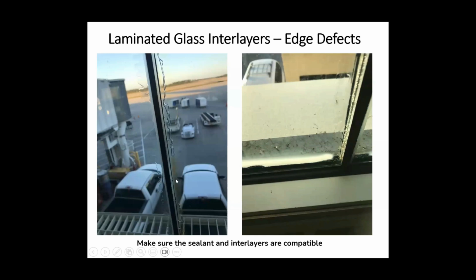Right, so I travel a lot out of the different Florida airports. So this one I actually took at the Orlando airport, not the new terminal, one of the older terminals. You can see this is a butt-glazed system where you have a sealant in the vertical, and there's bubbles, delamination on both sides of it. Now, I don't know why this is happening, but one theory is that the sealant is not compatible with the interlayer. I think in this case it's PVB, or somehow water got entrapped into the sealant.